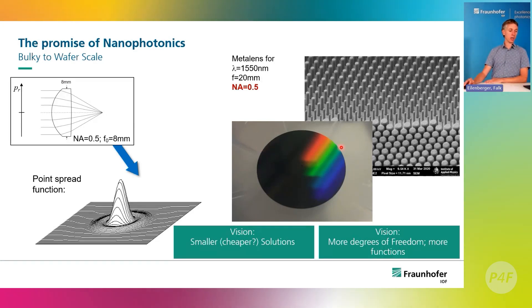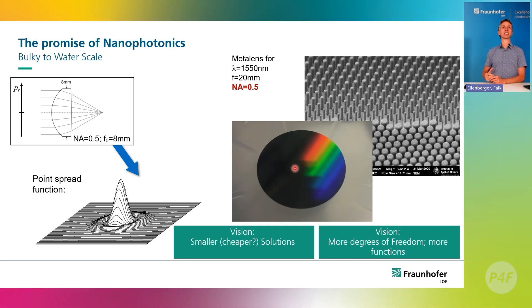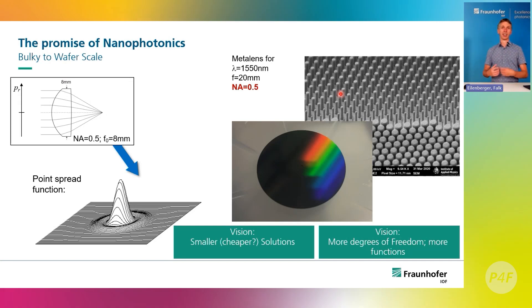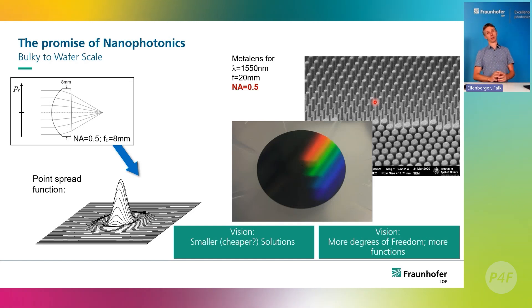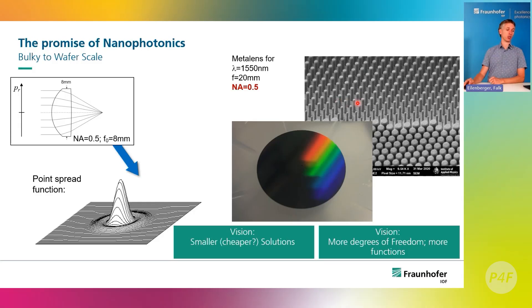What we have here is a glass wafer with a layer of silicon that is structured so that light propagating through it acts very much as if it has passed through a lens. Under an electron microscope, you can see the surface has been carefully sculptured into a series of silicon pillars, each roughly the size of the wavelength of light, acting like antennas. They take incident light, convert it into an excitation, and re-emit it. The effectiveness, angular properties, polarization sensitivity, spectral characteristics, and phase shift can all be engineered by carefully crafting each nano antenna — sometimes called meta atoms.